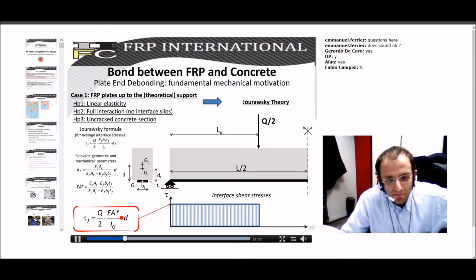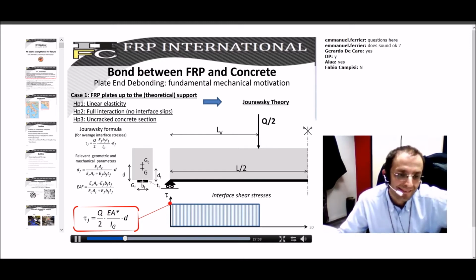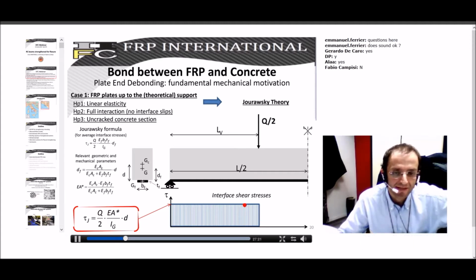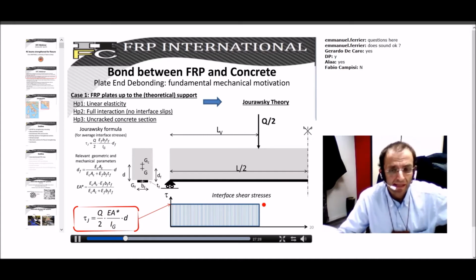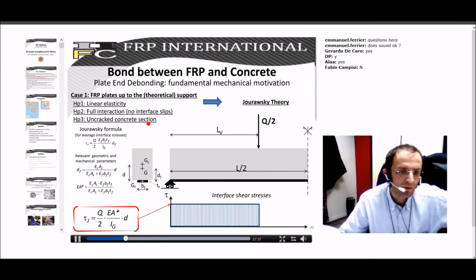But what I would like to emphasize is that, as you all know, in the case of an FRP strip running up to the theoretical support, tau, the interfacial shear stress, is similar to the shear force diagram. So we have a stepwise diagram. Here we have a finite value, which can be theoretically evaluated by means of this equation. And then we have a sharp discontinuity across the point in which the force is applied, and then you have zero shear force and zero interface bond stress. This is the case of a model based on these three assumptions.